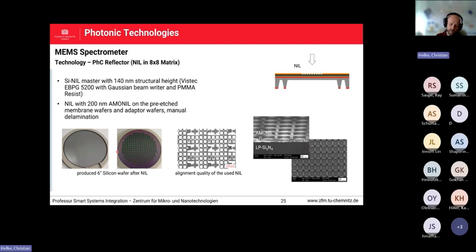Nano-imprint lithography works such that you press the wafer with a certain pressure to print the whole wafer. And so every wafer here has just 50 micrometer thin silicon membranes, and one has to find a process to get these processes running without cracking or destroying the whole wafers by nano-imprint lithography itself. But it works quite well.